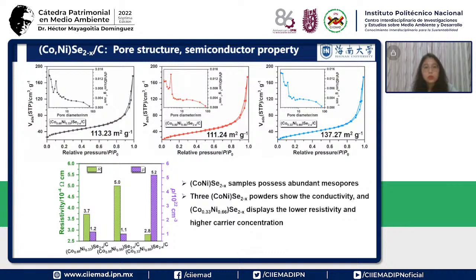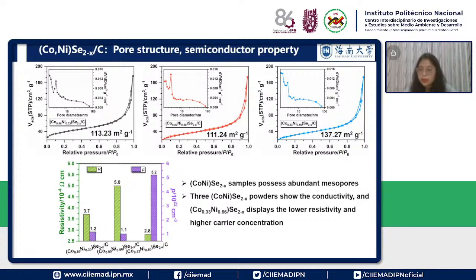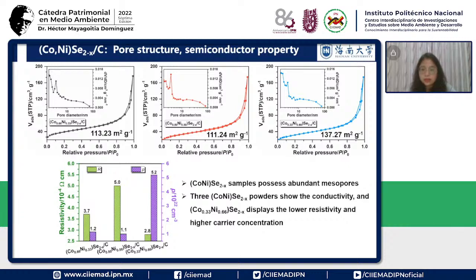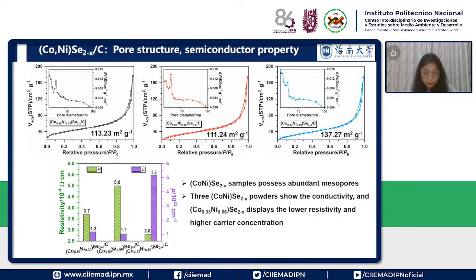And then in the next work, we continue to find some information about the pore structure and the semiconductor properties. In these three samples, the BET specific surface area values are similar, around 100, and the highest one is 137, on the material with the cobalt to nickel molar ratio of 1 to 2. These three sample powders also show conductivity. Especially the 1 to 2 ratio material displays lower resistivity and higher carrier concentration among these three samples.